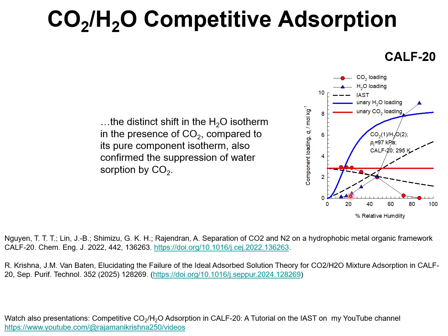Here is water sorption for mixture adsorption, shown by the blue triangles. For unary water, these are the loadings for water, shown by the continuous blue line. So the water loading in the mixture is significantly lower than the loading of the pure component, leading the authors of the science paper to postulate the phenomena of suppression of water due to the presence of CO2.